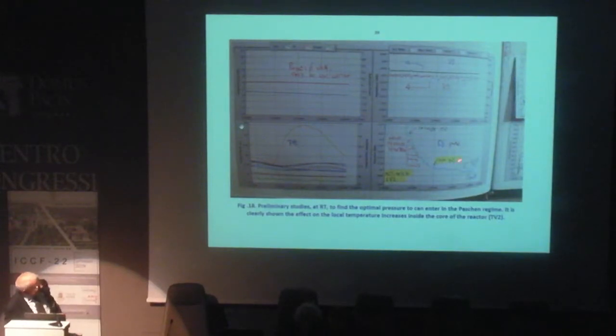In this study, at room temperature, we studied the pressure needed in our case to have a Paschen regime, and at the local thermometer increased the temperature when it started the maximum of the absorption. So, completely correlated. When the pressure was too low, nothing happened. So we are confident that we don't make a mistake.